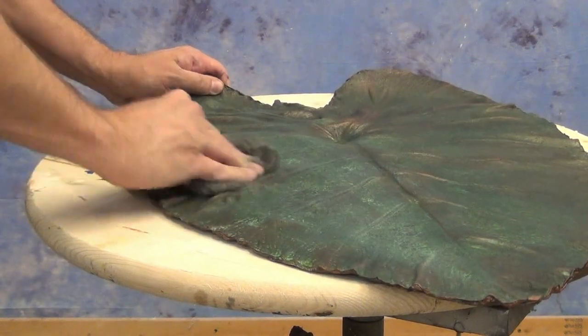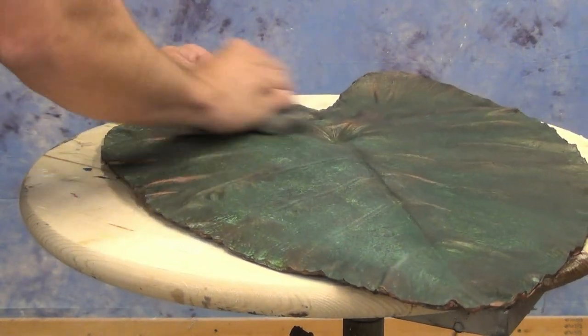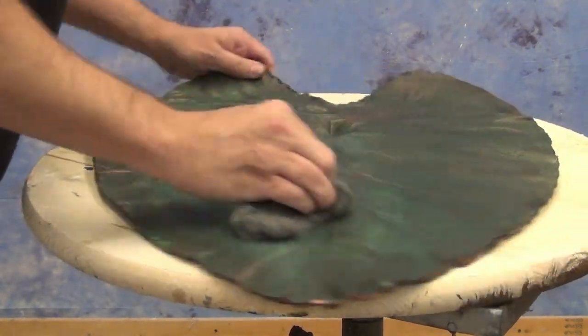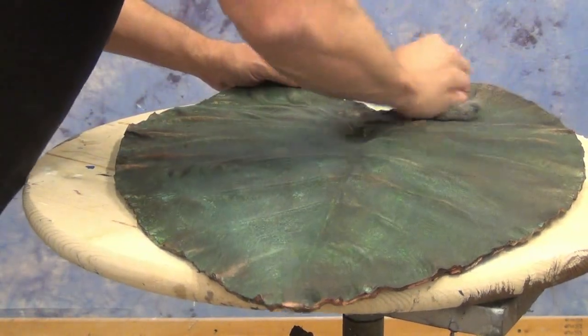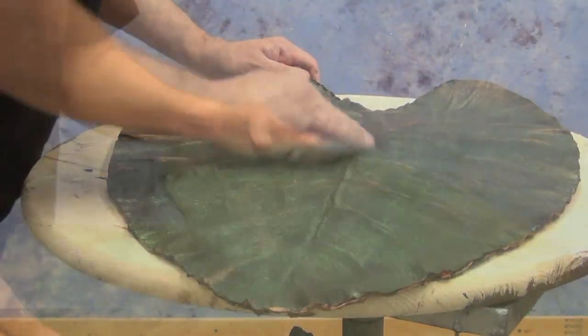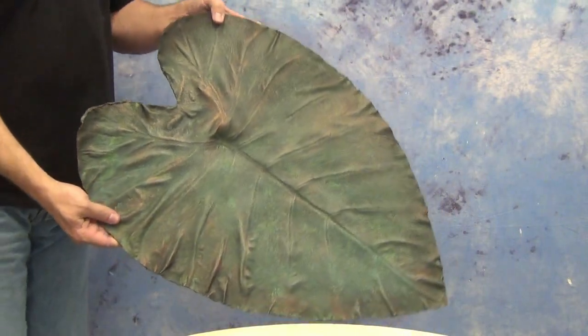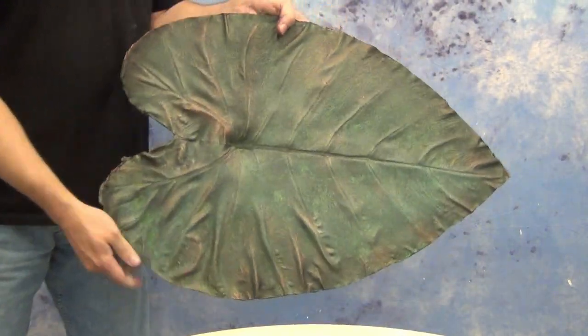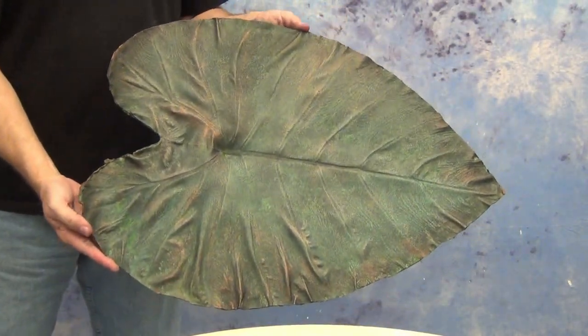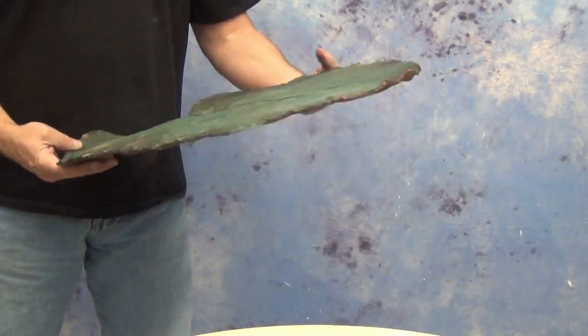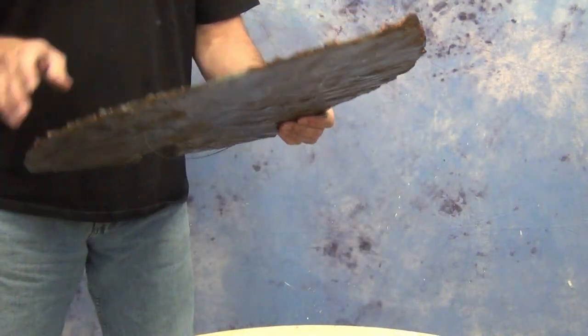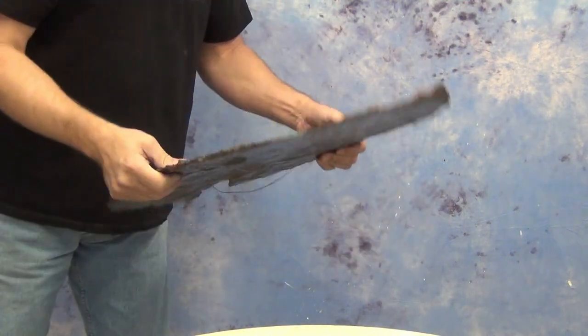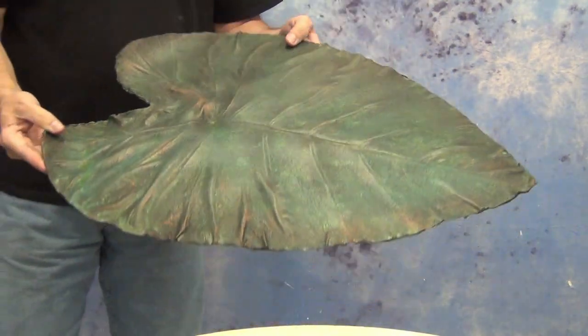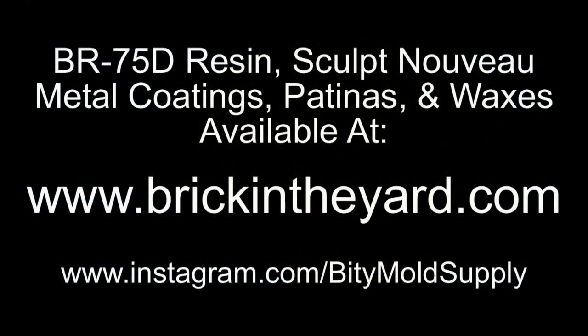And now that winds up giving us a very refined piece with more of a realistic antique copper, because we pulled back any of that excess black or any of the excess green on the high points, and we're left with a very nice antique oxidized copper look. Now you'll find that if you follow these directions that we did in this video, the powdering of the mold and the proper application of the primer and then the metal coating, if you follow those directions accordingly, you get a really good bond between the metal coating and the resin piece.